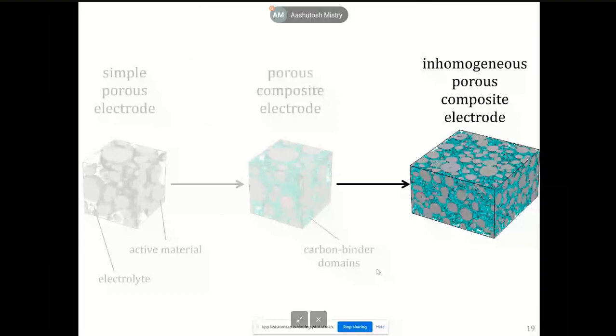So the magic figure you need to look at is about 1 to 2 Siemens per meter conductivity of the dry electrode. And the reason that figure comes out is because the ionic conductivity of the electrolyte is of the order of that value. So it's about 1 Siemens per meter. So as long as you are conducting faster than the ions in the electrolyte, you are not going to run into a limitation from the carbon binder phase.